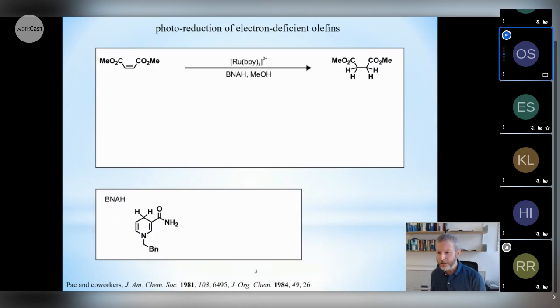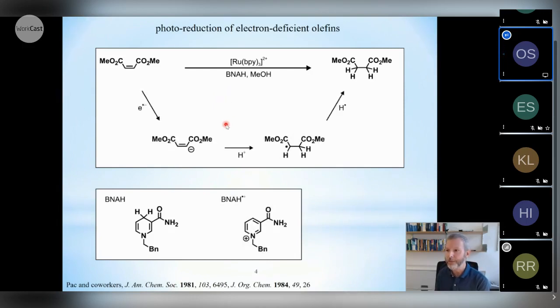This here is in fact an old study by Pac and co-workers, where they reduced these electron-deficient olefins with a sacrificial electron donor that looks a bit like the naturally occurring NADH, to these saturated versions here. And this was accomplished using Ru(bpy)3 as a photocatalyst in methanol. And this is very classical photoredox catalysis in the sense that it involves single electron transfer chemistry.